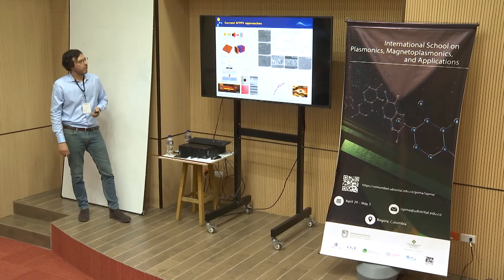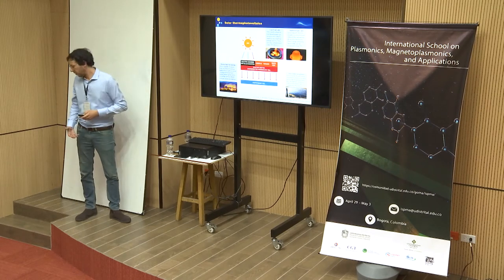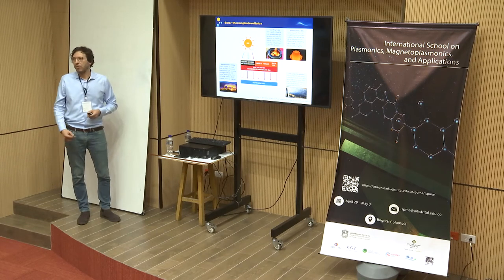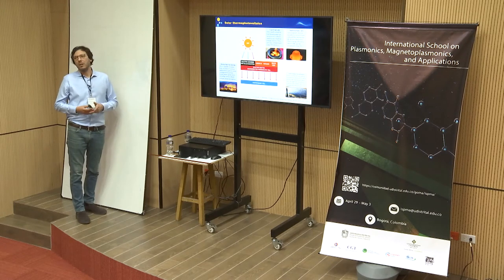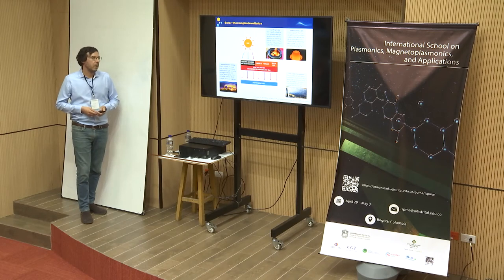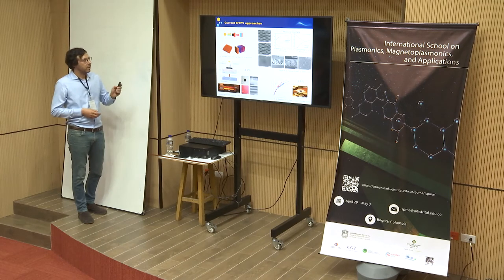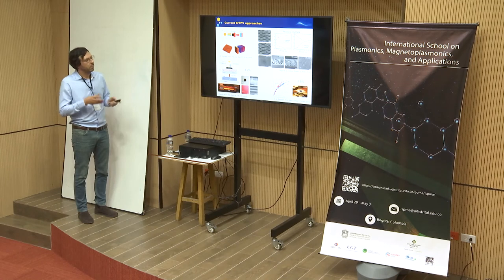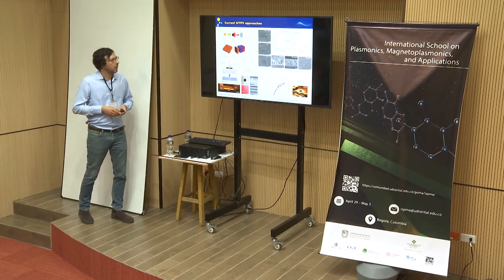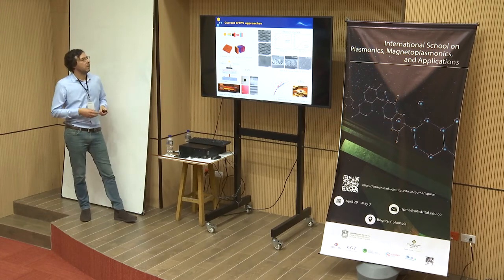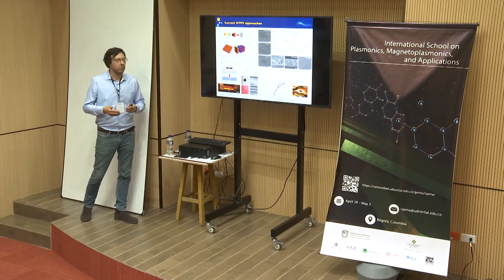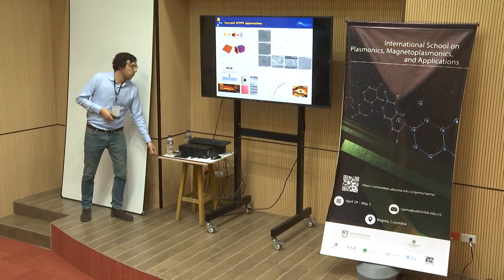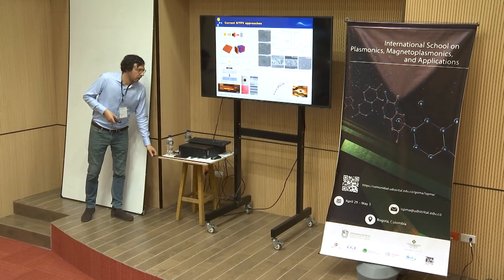As I stated, the main problem in the past was that there was no knowledge of how to design a selective emitter or absorber, and therefore with nanophotonics, plasmonics, and also dielectric resonators, this field really moved up to achieve interesting efficiency. Here are some examples of devices which have been realized by using, for example, photonic crystals with refractory materials, so tungsten, or covered with hafnium oxide to be protected, or other devices which use, for example, carbon nanotubes, as this one achieving 3.2% efficiency, and so on and so forth.